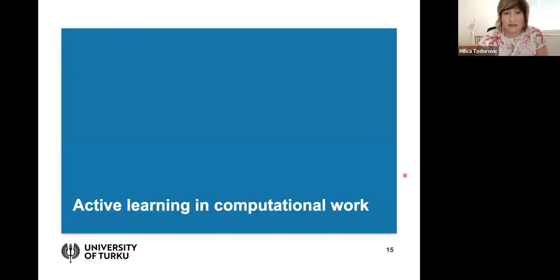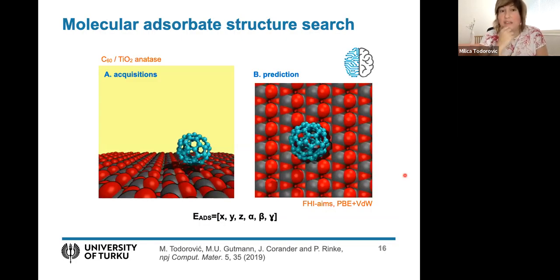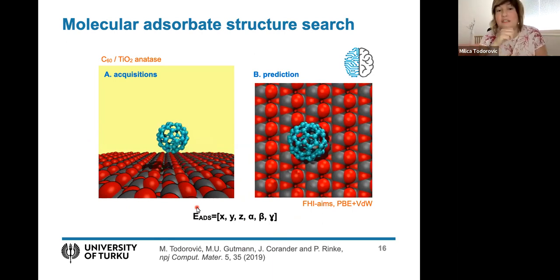So let's start with how to use active learning in some computational work. One thing that we are always interested in because of these functional interfaces are molecules on surfaces. So how does the contact form between the molecule and the surface? And one of the earliest studies we've done is molecular adsorption, where we were looking for minima over adsorption energy as we position the molecule differently above the surface and as we change its orientation.